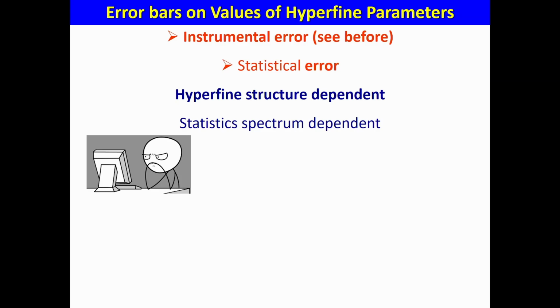Okay, error bars. Of course, when you are doing some experiment, there are some errors. Because you can control by doing some calibration on the velocity of your system, but according to the temperature, according to many parameters, there are small deviations. We have seen that the source has a line width. If you find something whose line width is smaller than the line width of the source, you have to be very critical. So of course, the statistics is very important. Sometimes it's much more difficult to fit with excellent statistics than with bad statistics. But there are some limits in both directions.